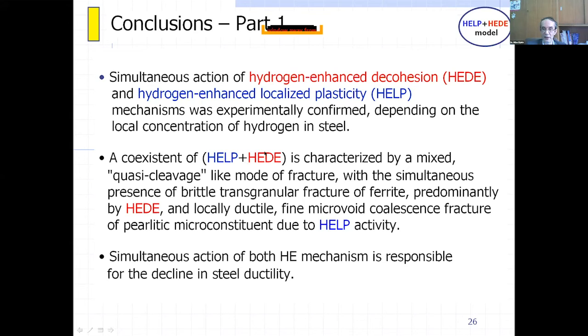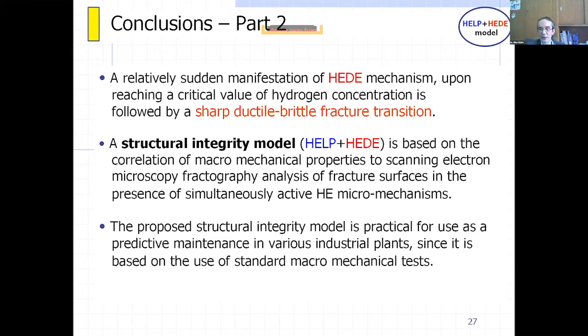HEDE is more effective and provides a sharp transition and a sharp drop in mechanical properties, including ductility. A relatively sudden manifestation of the HEDE mechanism upon reaching a critical hydrogen concentration is followed by a sharp ductile to brittle fracture transition. And our structural integrity model, developed over more than 5 years, is based on the correlation of macro mechanical properties to scanning electron microscopy fractography analysis of fracture surfaces in the presence of simultaneously active hydrogen embrittlement micromechanisms. Finally, the proposed structural integrity model is practical for use as predictive maintenance in various industrial plants since it is based on the use of standard macro mechanical tests.